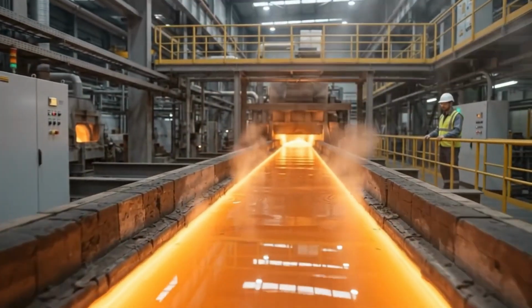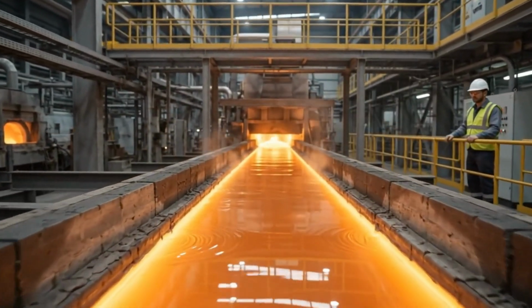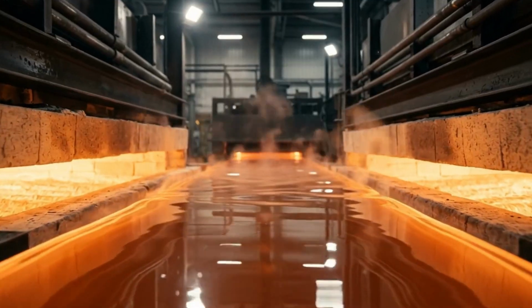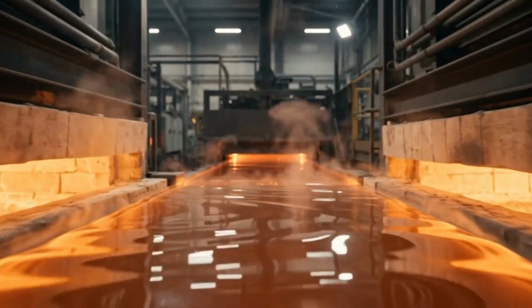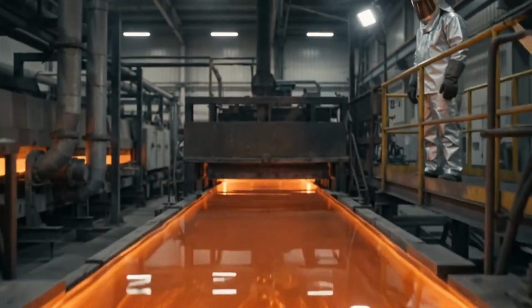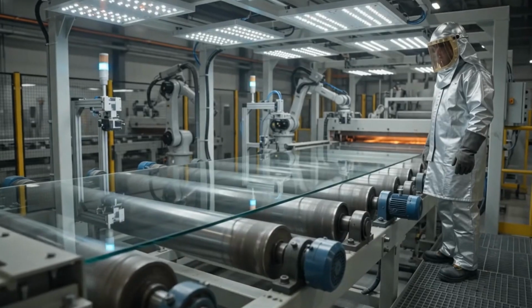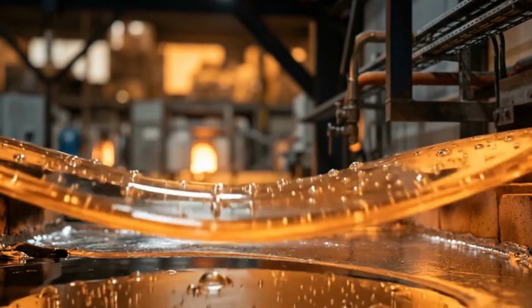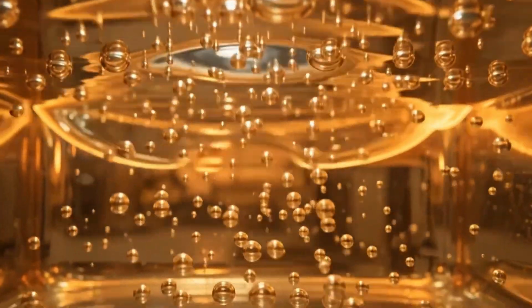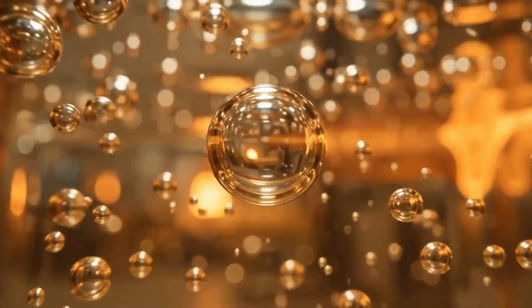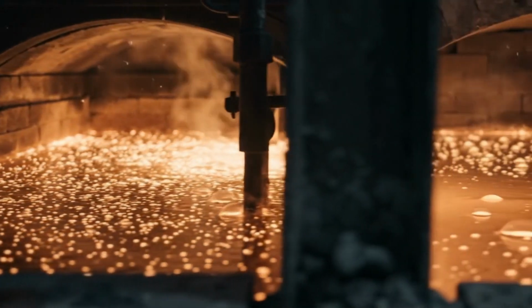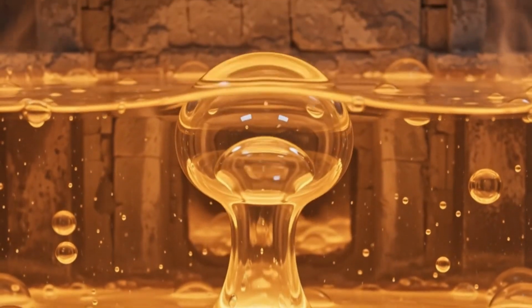As the molten glass moves through the furnace, the raw materials release gases that become trapped inside the glowing liquid. If those bubbles remain, the finished glass won't be perfectly clear, and for many products, that's simply unacceptable. So how do engineers remove something they can barely even see? The answer is patience and physics. Instead of rushing through the furnace, the molten glass flows slowly into refining zones where temperatures are carefully controlled. This gives the bubbles time to rise naturally to the surface and escape.